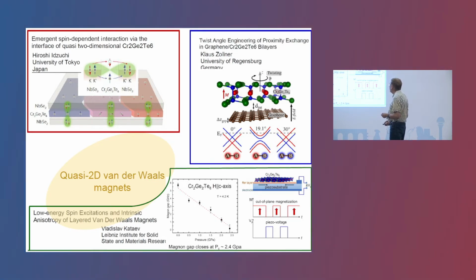Actually, they also found a very interesting phenomenon of enhancement of the critical temperature of this material deposited on a special tensile substrate, which expands the crystal lattice. And by definition, I had to attend my own talk on this subject, where we reported on the pressure-dependent change of the magnetism in this material, namely the suppression of the ferromagnetic order by applying a compressive strain. That was a really good interplay with the results of Dr. Idzuchi, where they found that if one expands the structure, the ferromagnetic order gets more stable.